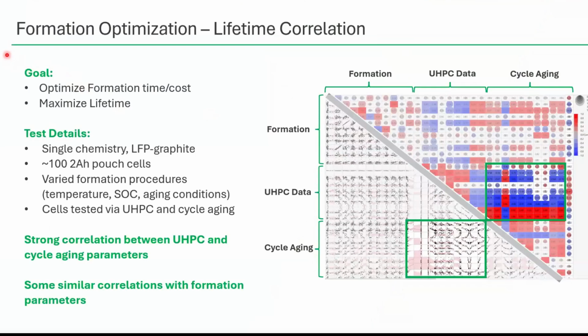We took a single chemistry, LFP graphite, and over 100 pouch cells, these are 2 amp hour pouch cells, and varied all the formation procedures, varying different temperatures for storage, aging SOCs, et cetera. Then we took the cells and moved them into UHPC cycling for a couple of weeks and cycle aging until they reached 80% state of health.